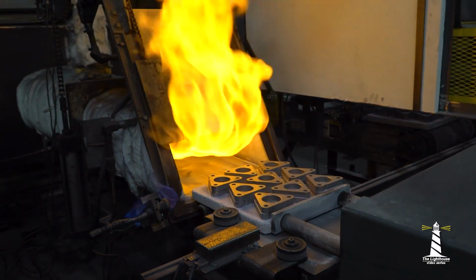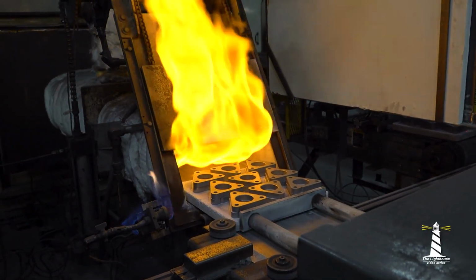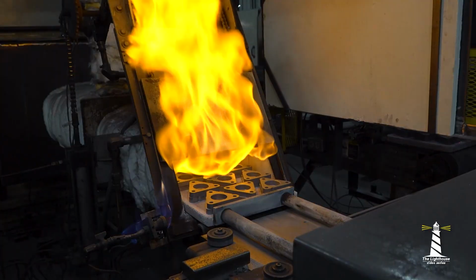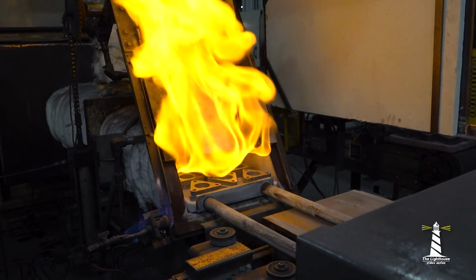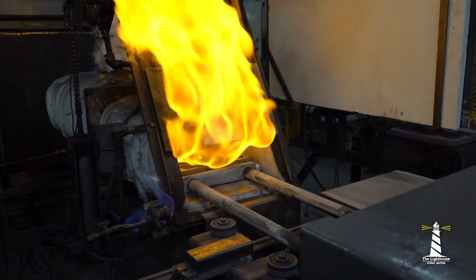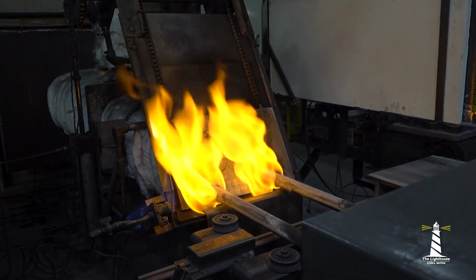And the belt can survive at that temperature. For the higher temperatures, up around 2500, 2600 Fahrenheit, the belt would stretch out and in some cases just deteriorate very quickly. Right. So we use little high temperature resistant boats that we put the parts on, and then the furnace just pushes in one boat every minute or a couple of minutes, and it takes just as long to sinter them, but it's just at a much higher temperature.